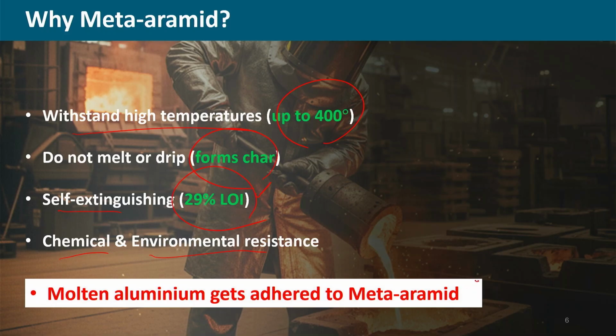But the problem here is that the molten aluminum gets adhered to the meta-aramid surface. So, this is the problem here. So, it has got advantages. Some advantages over the wool, like high temperature withstand, it can do prolonged temperature withstand of 400, which is better than wool. Do not melt and drip. So, it is equal to wool. Self extinguishing, it has higher LOI, better than wool. Chemical and environmental resistance, much better than wool.